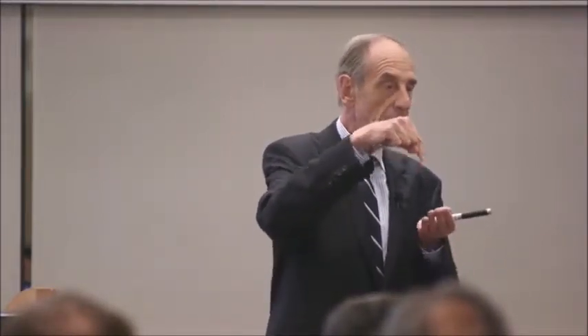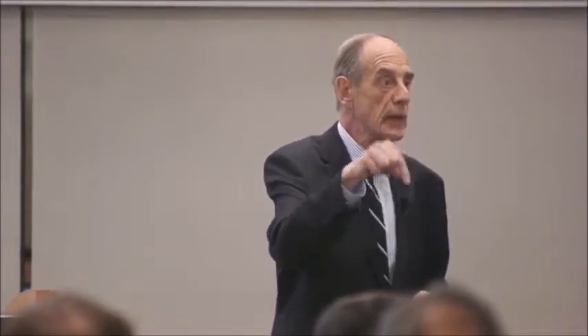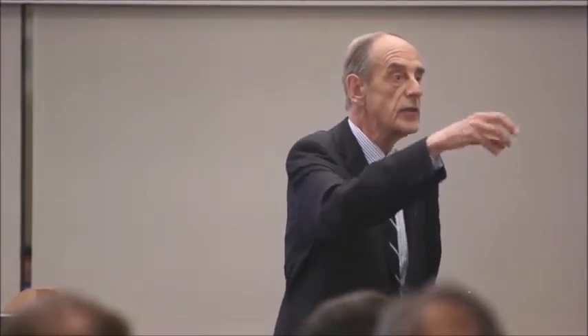Because these very modern instruments, like the one which is available in Sendai, and we have one, can get a diffraction pattern of about 0.5 nanometer in size. And we hope that by these diffraction patterns we can say what kind of configurations we have in these interfaces. In the case of what I showed you,